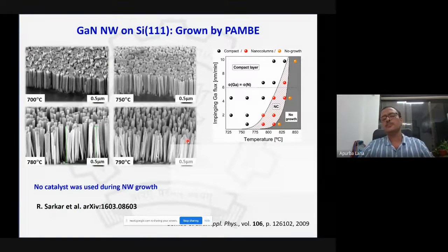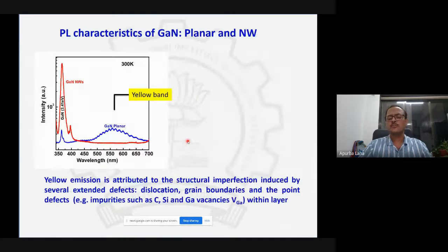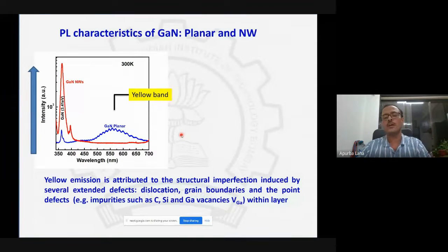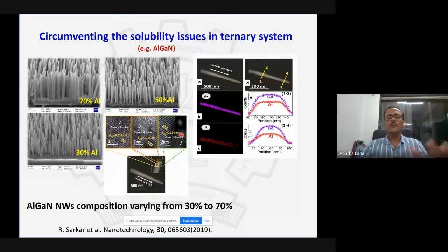Now, the interesting thing is, if you look at their optical properties, I'm not going to go into details of the growth, they are very unique and very useful. This is the room temperature photoluminescence measurement of a planar layer of gallium nitride and the nanowire that we have seen in the previous one. So you see the yellow luminescence is not present here, it's missing. That shows that there is a huge improvement in the structure by moving into nanowire based structures.